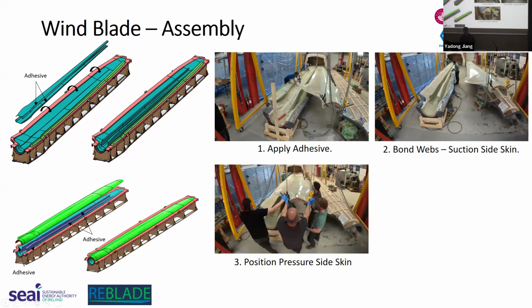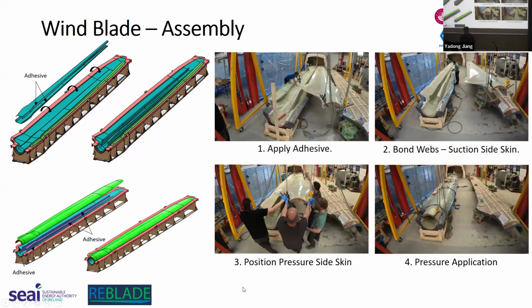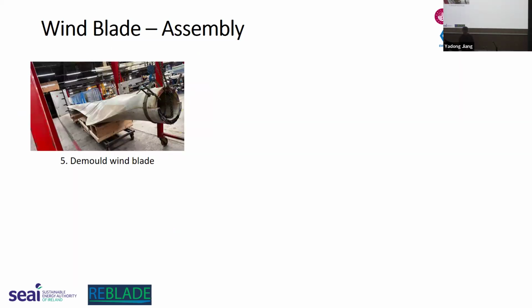And then we bring the suction side skin, or sorry, the pressure side skin over, and we position it in place, and then we apply pressure. Pressure application for the full scale blade was done with ratchet straps and timber, just to try and evenly apply pressure across the bond lines. And then that was left in place for about 24 hours to cure, and then it was put into an oven for post curing.